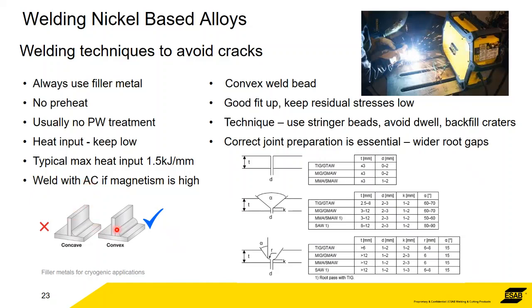This little diagram here is explaining the need to use a convex weld bead rather than concave. So if it was a butt weld, we'd rather see more weld metal on the surface rather than a flat weld, or a concave for a fillet. The idea being that you need sufficient metal in there to hold everything together. Otherwise it won't have the strength to hold everything together as it starts to cool down. That's when you start to see some cracking.